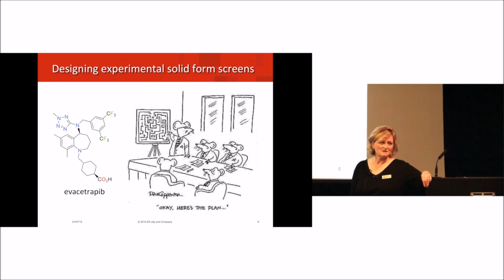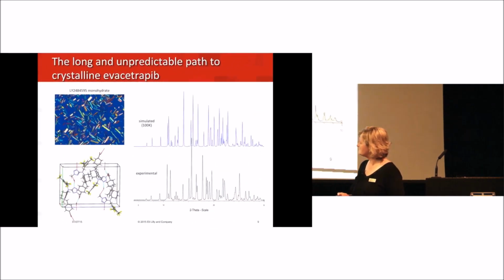This compound would not crystallize for us at the point in time shortly after the compound was nominated. I don't recall a compound in my 20-some years that we have tried that hard to crystallize, and it just would not crystallize. And so we finally got to the point where we realized that we're probably going to have to develop an amorphous dosage form here, even though we really didn't want to. And there are other issues to go with that. And so we continued with the development of an amorphous form, but there was still some solid state screening going on. And within 1 week of this compound being nominated, it finally crystallized.